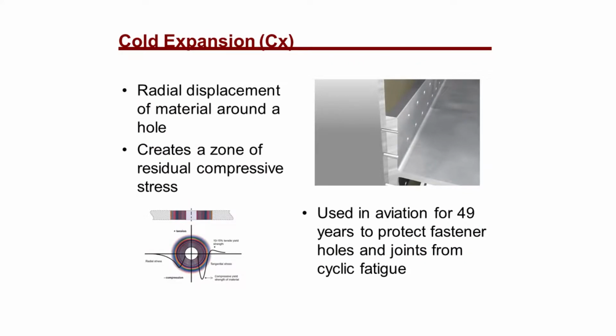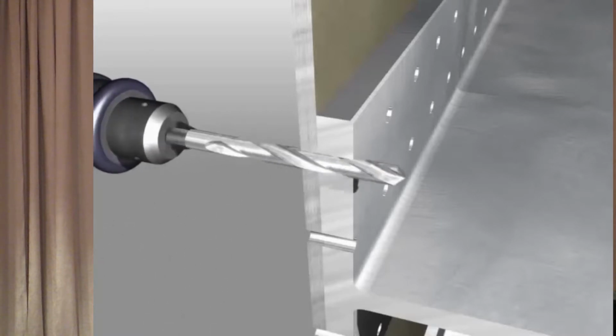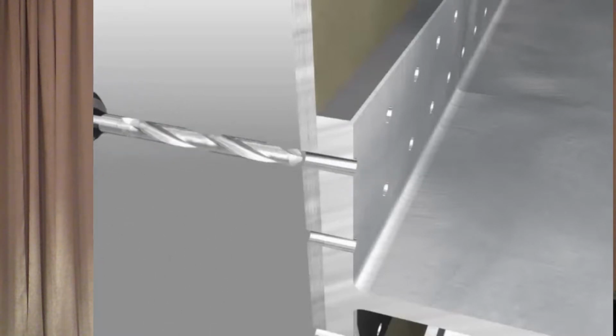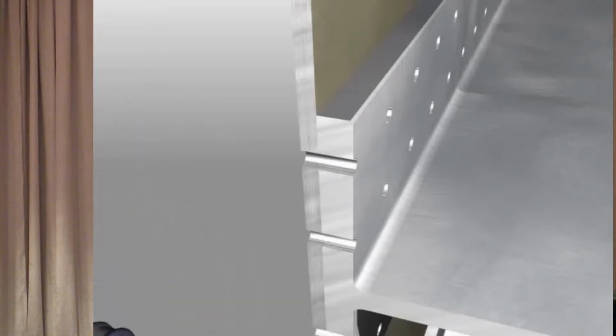Cold expansion itself, the basic process, is about radial displacement of a material around a hole in order to generate that zone of compressive stress. So here's a quick video explaining how that works. You have to have a very precisely sized hole. For aviation, that hole has typically got a 3 thou tolerance. For our crack mitigation process, it's a 2 thou tolerance.